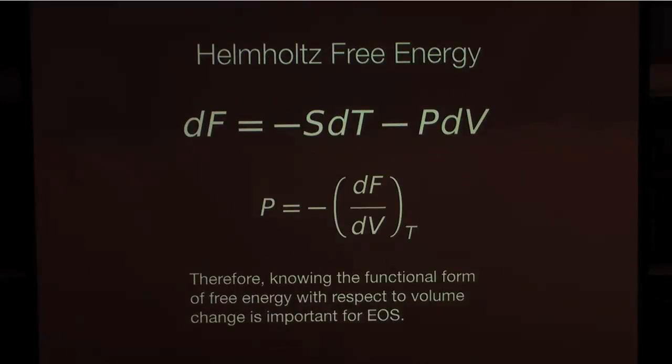So now I'm going to move toward the more modernized equation of state by Vinet et al. The idea Vinet developed is a very simple but theoretically sound approach where he used the thermodynamic notion of free energy, related to temperature and volume change, particularly volume change. What this equation tells you is that if you know the functional form of free energy as a function of volume, then you should have a theoretical equation of state, right?